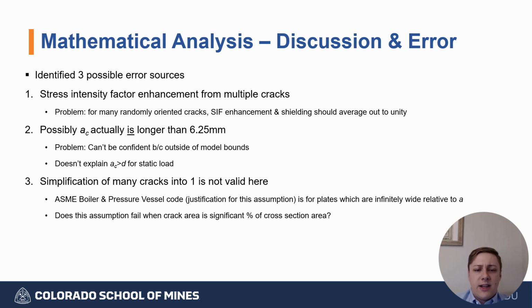The second possibility is that the calculations are correct and the critical crack length is actually longer than the 6.25 millimeter limit. However, this does not explain the fact that for some of our load conditions, the critical crack length was longer than the diameter of the bar. And we also cannot be confident in this answer because it falls outside of the model range. So we're left to conclude that the most probable source of this departure between the model results and what is physically observed is that the assumption that many adjacent cracks can be treated as one crack of a single effective length is not valid here.